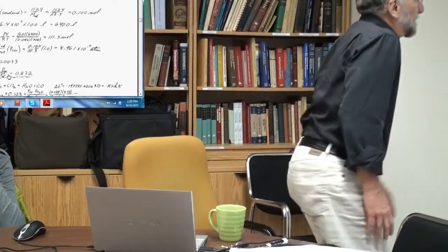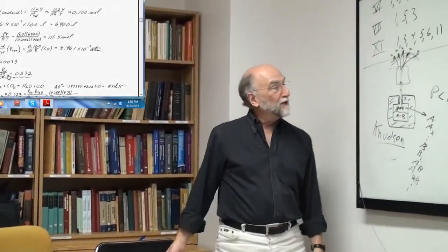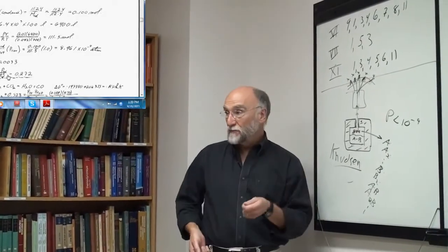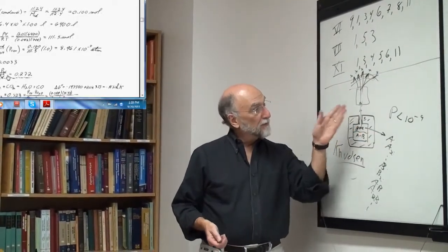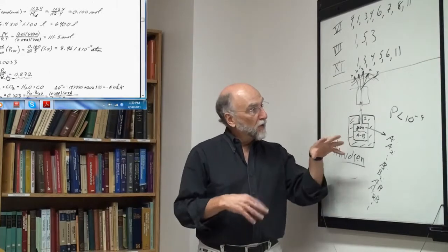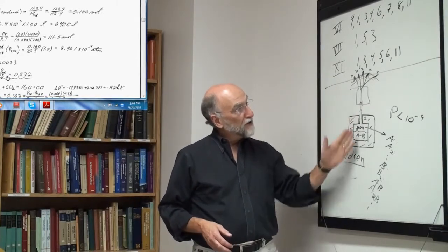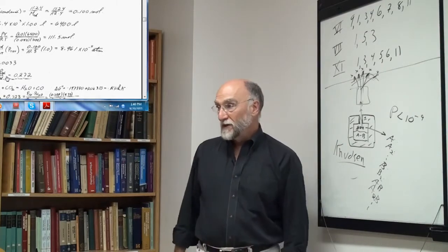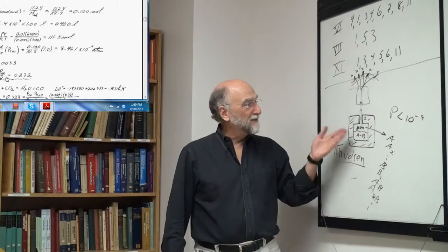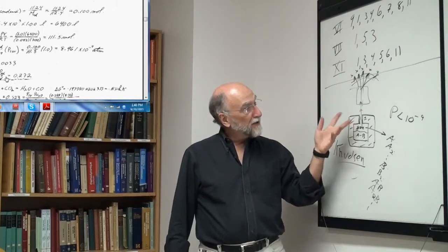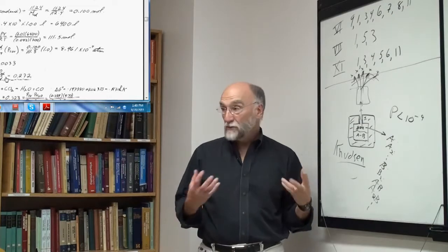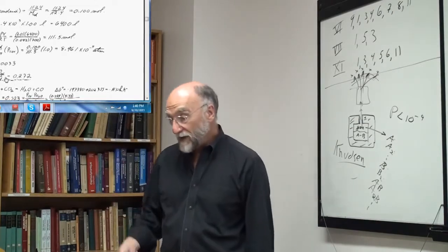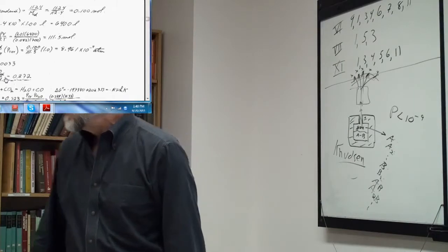Why does the orifice length have to be less than the mean free path of the gas, just to avoid collisions? Yeah, apparently, and I won't pretend to be an expert in the theory, if you have too many collisions among the molecules themselves and with the walls of the hole and everything, then the equations that relate the number of molecules leaving to the partial pressure become basically insoluble. In the equations some of the collisions are taken into account, but you're assuming there are not too many, that they're pretty much independent. Otherwise, I understand you just can't really resolve the thing.